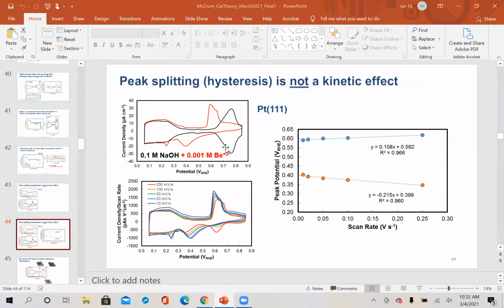Sure. So thanks for the question. I'm not entirely sure how to answer that because I don't know how detailed of a comment you're looking for. So I can tell you, typically we're using a unit cell of a fixed size, and to vary the coverage, we're varying the number of adsorbates in the unit cell. And so if we want to vary the hydrogen coverage, in a 3x3 platinum 111 unit cell, we're adding 1 to 9 hydrogen atoms to model 1/9 to 1 monolayer.